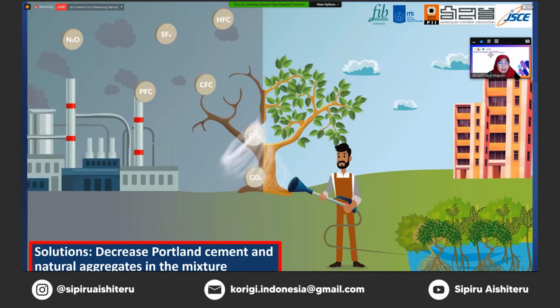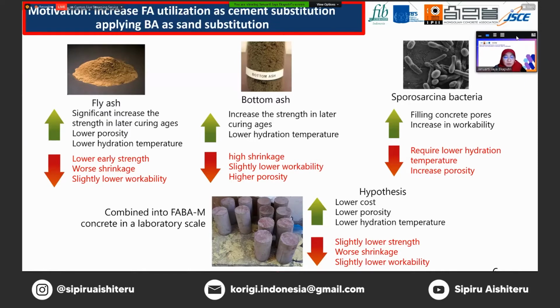We increase the utilization of fly ash in concrete as a main replacement, as a cement substitution up to 50% by cement weight. It is not as much as Sagawa Sensei's explanation before, but we have done our best. It has a positive and negative effect to the concrete. It increases the strength at the later age. It has also lowered the porosity and decreased the hydration temperature. However, as a pozzolan, it has a lower strength at the early age and contributes to high shrinkage and makes the workability lower if we use more than 30% by cement weight.